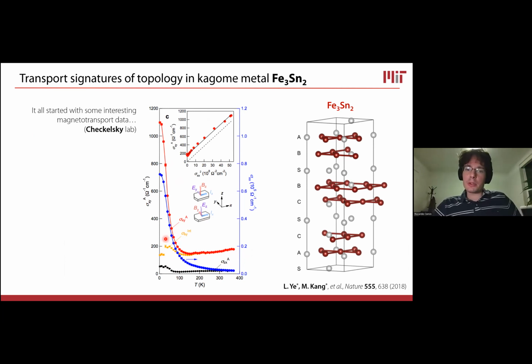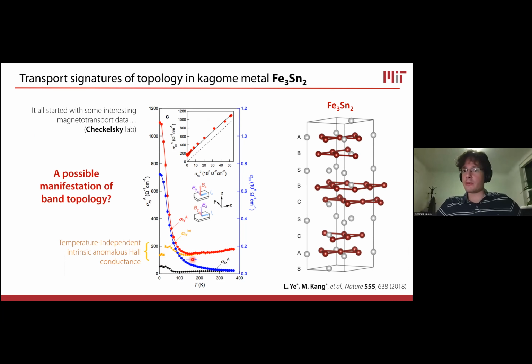But then in addition to this contribution, which kind of vanishes at high temperatures anyway, there is another contribution which is almost temperature independent and cannot really be explained with a scaling of the longitudinal conductivity. And so this contribution must be intrinsic. And it's temperature independent, which suggests that it's potentially a manifestation of band topology. So something which is completely intrinsic to the electronic band structure that underlies the macroscopic transport measurements.